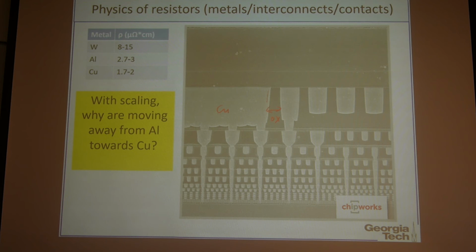So you need some barrier actually here. You see actually in this image, there's a little bit lighter region. So that is the barrier to prevent the copper atoms from going into the oxide. And typically this barrier is TaN, the tantalum nitride. So we can use copper because there is a very good barrier, this tantalum nitride, but there's no good barrier for silver. Okay.